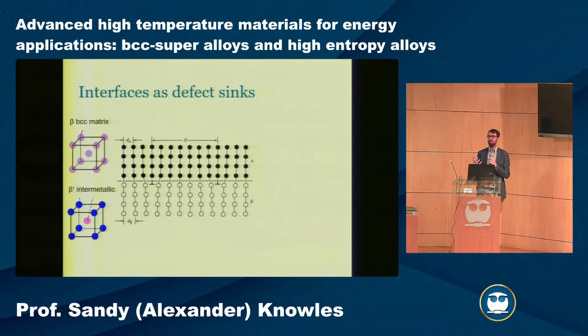Here we have, again, the interest of trying to develop high temperature strength, but we're also now looking at a radiation environment. When you irradiate a material, you bombard the lattice sites with an incident particle, which might be a neutron or a high energy ion. As the particle hits into the lattice, it's going to disrupt and create a cascade of damage. When you impact and irradiate a material, you tend to create a lot of vacancies and dislocations, which create defects within the materials. Those will harden the materials, but also potentially embrittle them.